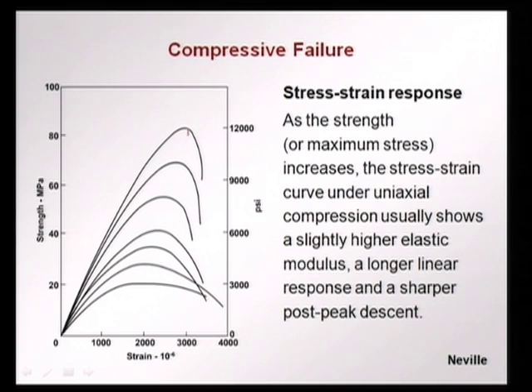What is very important is what happens after the peak. When you observe the stress strain curves of lower strength concrete, we find that there is a gradual drop in load carrying capacity, a gradual drop in stress, and when we have higher strength concrete, there is a very sharp drop in the stress. That means the material fails in a very brittle manner, there is not much load carrying capacity once the peak is reached, and the concrete fails in a sudden manner. That means higher strength concrete, as we discussed in the previous lecture, is much more brittle than lower strength concrete. So, we have to take this into account in design, and we have to use the proper stress strain diagram in design in order to represent this change in behavior as the strength increases.